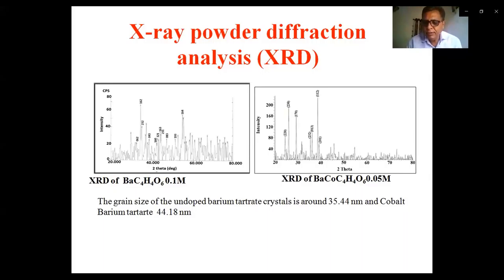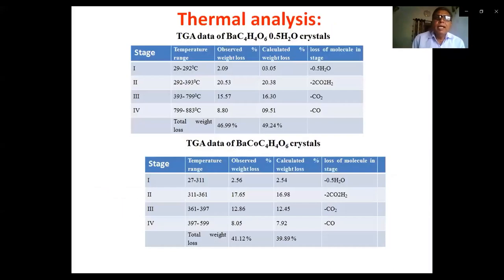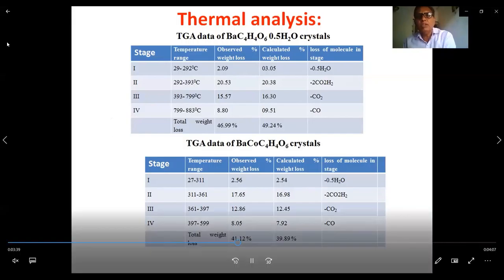In thermal analysis, the TGA data of barium tartarate shows four stages, with temperature starting from 29 to 292, and the end of the fourth stage is 799 to 883 degrees Celsius. The observed total percentage weight loss is 46.99%, and the calculated percentage weight loss is 49.24%. The loss of molecules I have shown in the chart.